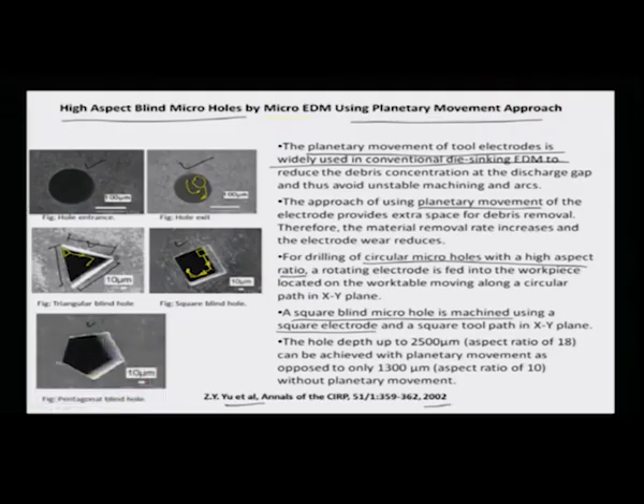Okay, in fact all these holes are to the depth of about 2500 micrometers, and if you look at one of these edges here, for example this particular edge, if this is 10 microns, this must be close to about 130 or 140 microns. Okay, so having said that, a very good aspect ratio of the order of close to 18 or so is generated using this kind of a process. So it is actually a very good and capable process for doing high aspect ratio structures at the micron scale.